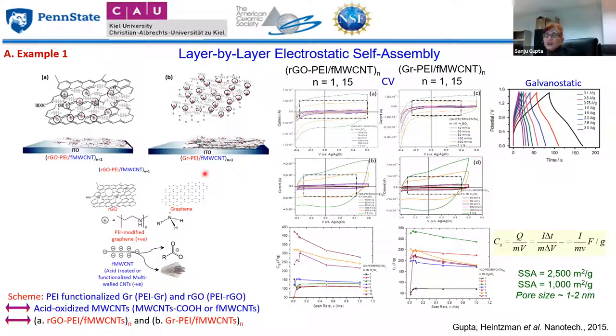So here we are using an approach we call layer by layer electrostatic self-assembly. What does that mean? We have a graphene with a certain charge, and then we functionalize it with polyethylene imine so that it acquires a positive charge, and then we have a functionalized multiwalled carbon nanotube, which has a negative charge. So we know positive and negative attract. This is the electrostatic strategy to combine the two systems. This is what we call all-carbon supercapacitors.